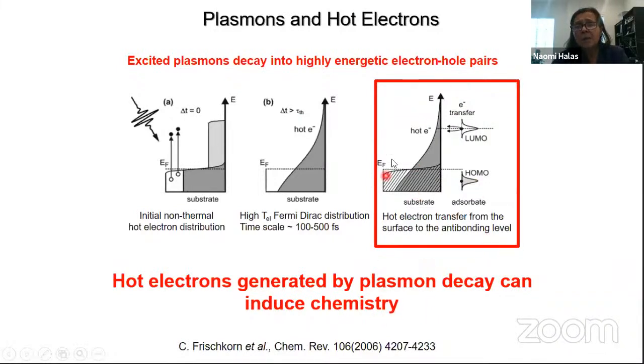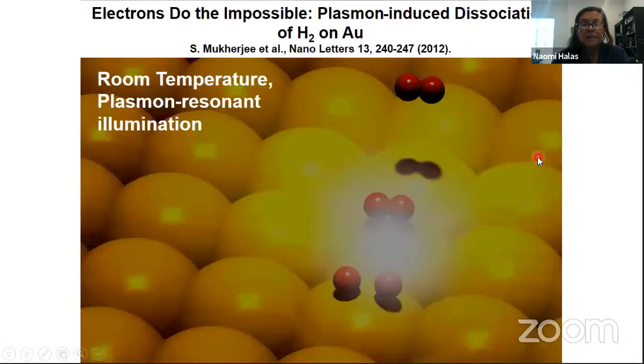One particularly simple form, which I'll show you in a moment, is the case where we have a hot electron that transfers to a LUMO level. All of a sudden, what used to be a neutral adsorbate can now be negatively charged. So we have what is called a transient negative ion sitting on the surface, and that lowers the barrier for a lot of different chemical transformations. It can undergo chemistry once we go from a neutral state to a negative ion state. So let's see an example of this.